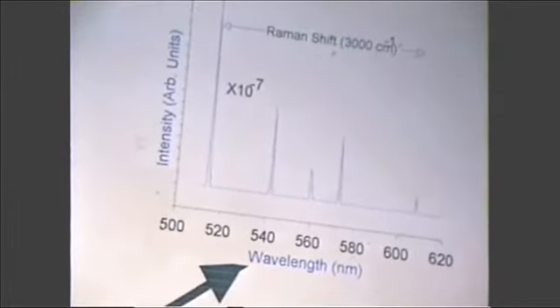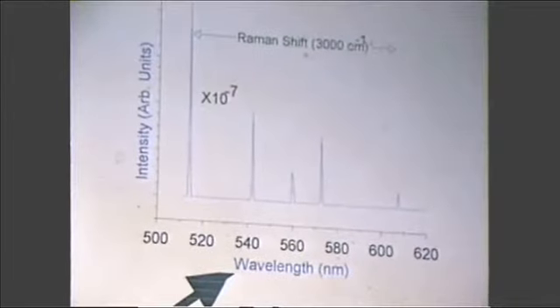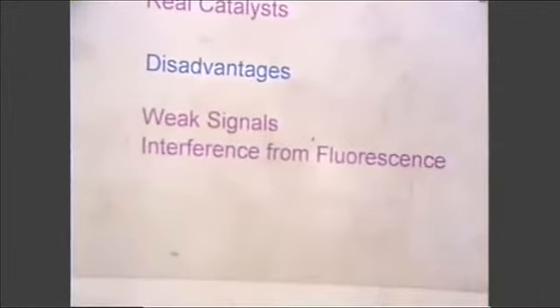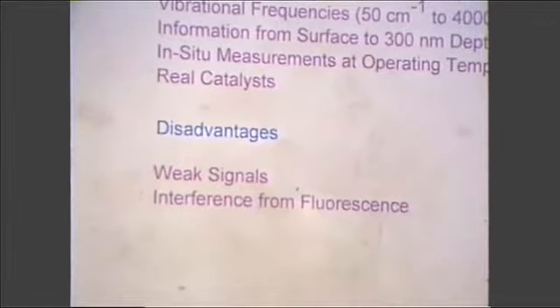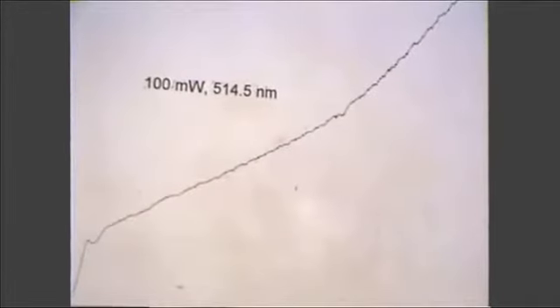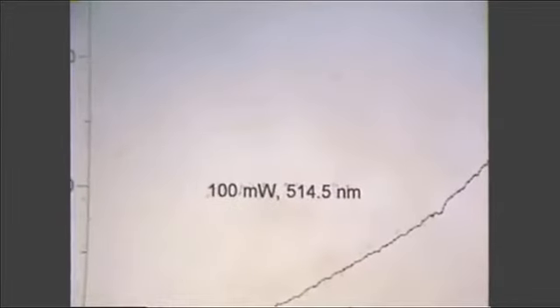The first one is that the signals in Raman scattering are very weak. So on this little diagram up here, I have to attenuate my green light that scatters from the sample by a factor of 10 million to get it on the same scale as the peaks from the Raman scattering. So these are very small intensities. And the other problem, which is really the main one for application of Raman scattering to hydrocarbon catalysis, is the problem of fluorescence. Very often, when you look at a catalyst sample and try to measure the Raman spectrum, you get something that looks like this. So this is a spectrum from a deactivated rhodium on alumina catalyst. So this catalyst has been coked. This is a sample that I got from one of my friends at Amoco.